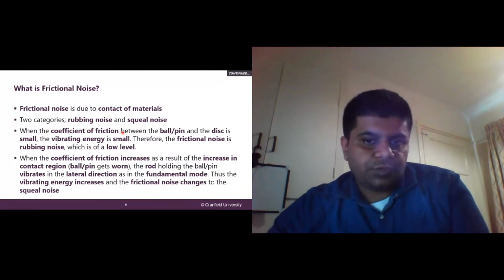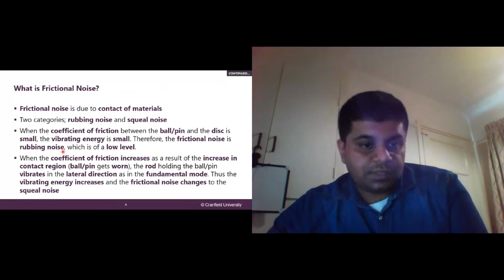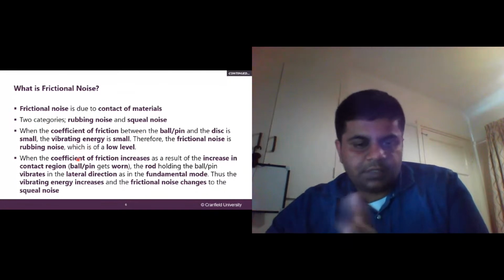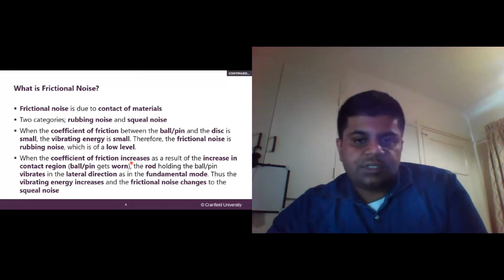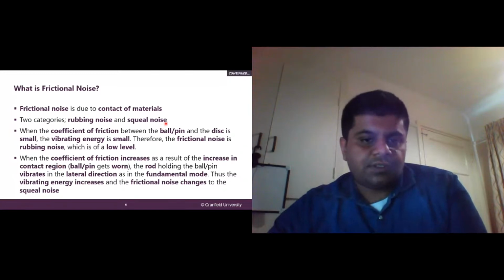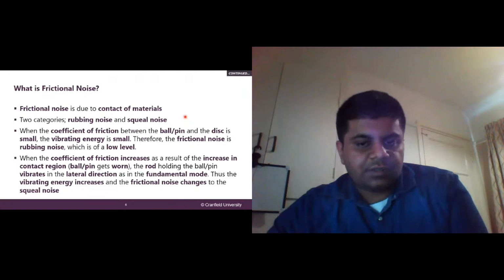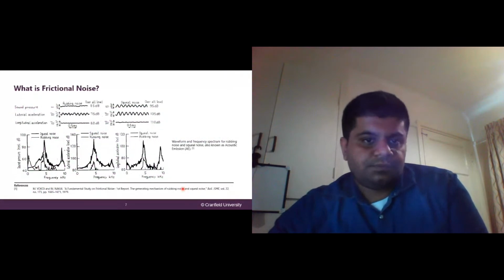So when the coefficient of friction between ball pin and the disc is small, the vibrating energy is small, and therefore the frictional noise, or rubbing noise, is at a low level. And exactly what I explained right now, when the coefficient of friction increases as a result of increasing contact region, ball pin gets worn and the rod holding the ball pin vibrates in lateral direction, which increases the vibration energy and leads to higher frictional noise, which is also known as a squeal noise.